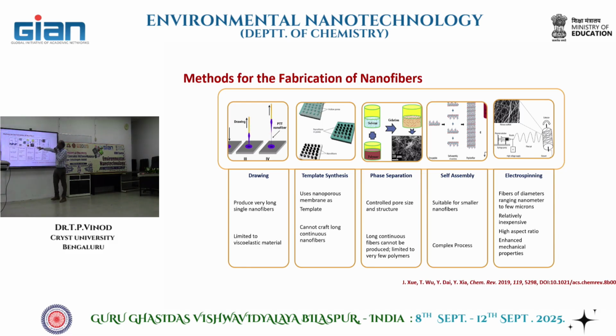Then another way of doing it is phase separation. You have a polymer which is dissolved in a solvent, and the solvent is not a very good solvent, and you add another solvent onto that, and these two solvents are not miscible with each other. Then you have an interface, and this polymer has some affinity to the solvent which is on top. So from the solution, it will move up to the interface, and at the interface you get a film, and that film can be in the form of nanofibers if you add certain surfactants, and also some soft templates which control the morphology of the interface. That's one way.